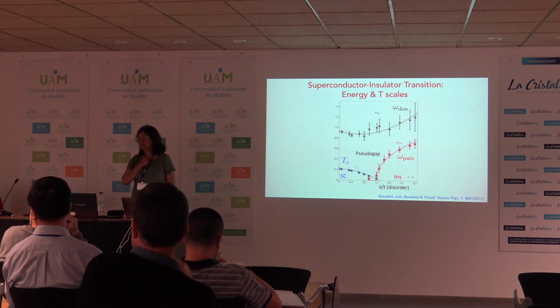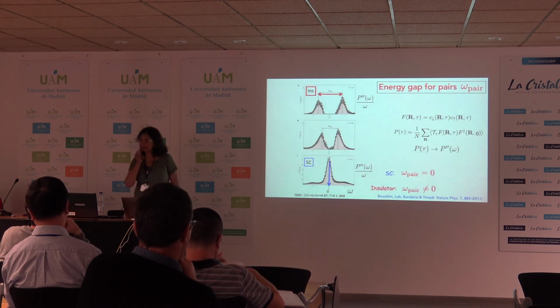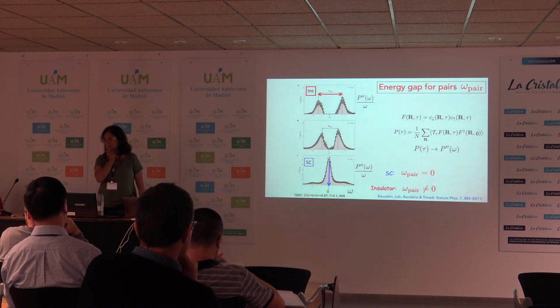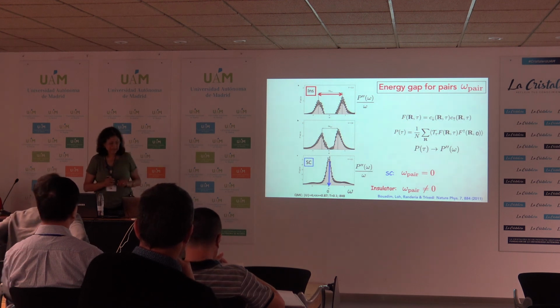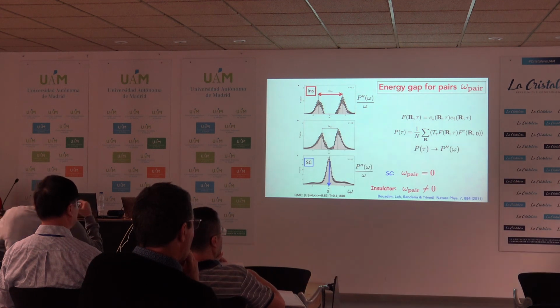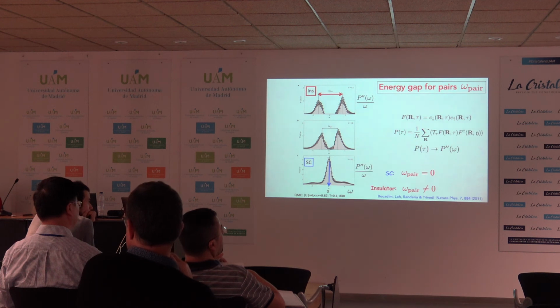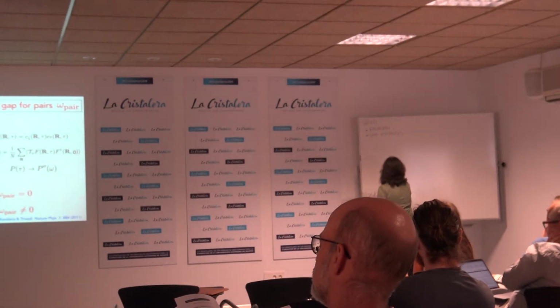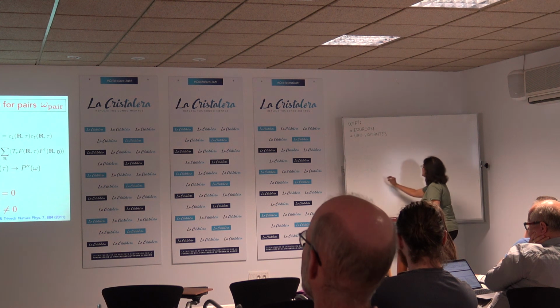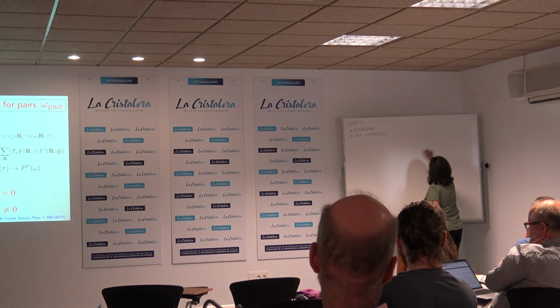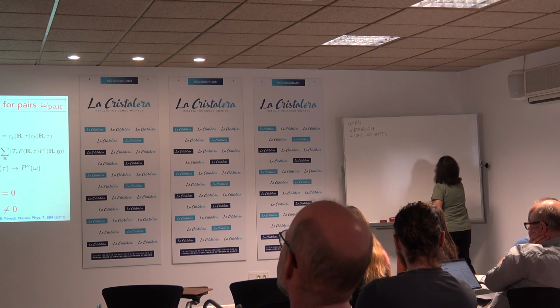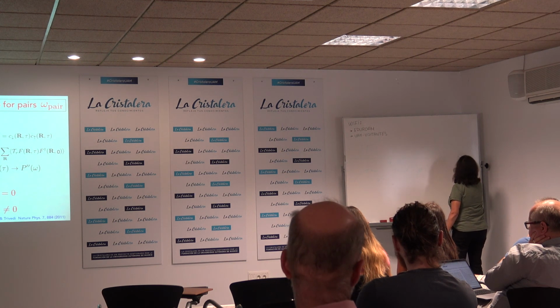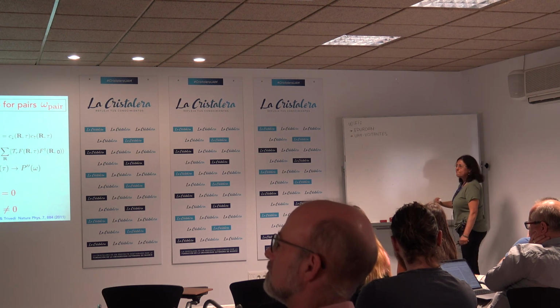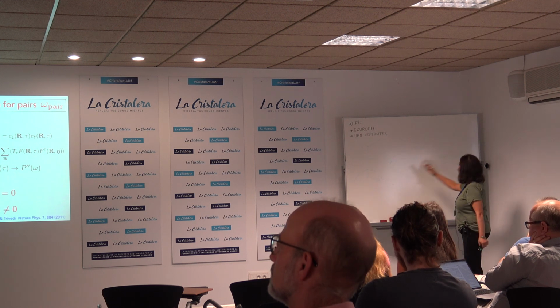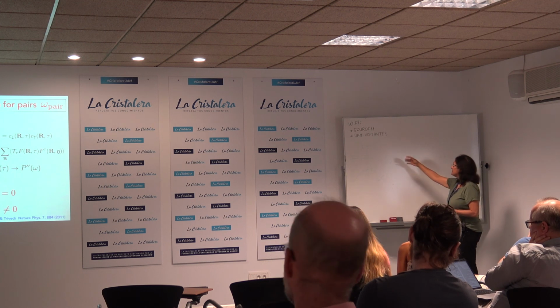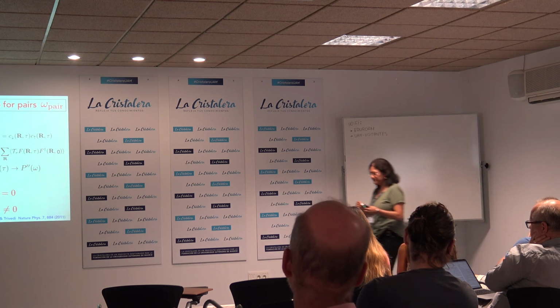In the previous transparency that you showed, if you try to tunnel with a superconducting tip, you will see a Josephson effect on the bottom situation, right? So what you would see, let me just do this picture here. If this is V and that is I, you would see some critical current on the superconducting side. Then just at the transition, this would become linear. This is at the transition. And then beyond that, it would become more like this IV. So this would be a very nice experiment, to go through the transition and see the switching from sort of a phase qubit to a charge qubit kind of transition.